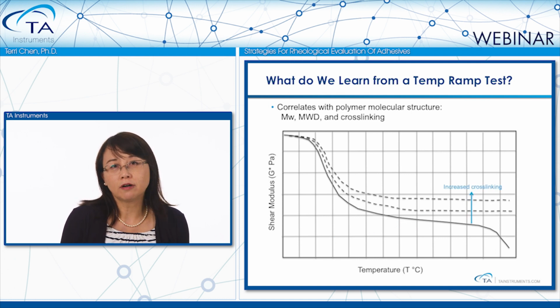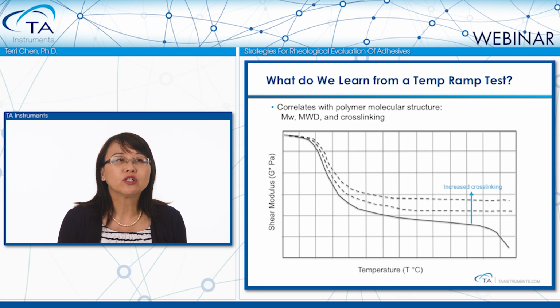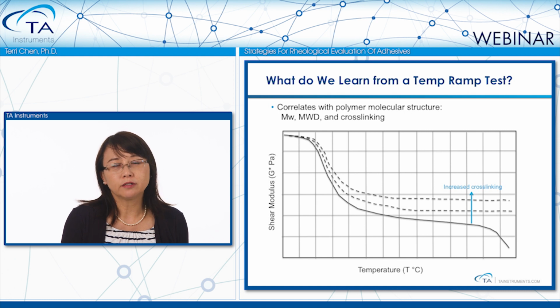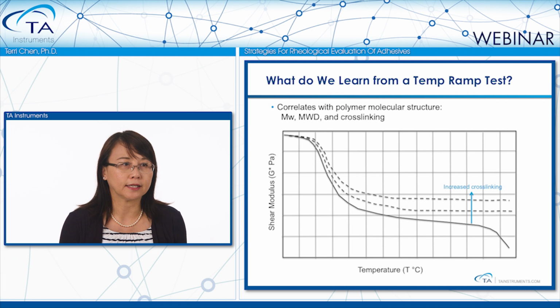If the polymer is cross-linked, first, it will show a higher Tg compared to the same polymer that is not cross-linked. Also, the rubbery plateau modulus of a cross-linked polymer will be higher. The shape of the curve will be more flat and extend to much higher temperatures. A cross-linked polymer will never melt. In some literature, people use the rubbery plateau modulus value to quantitatively calculate the degree of cross-linking.